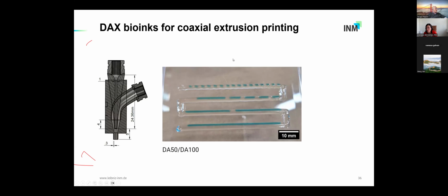So we use coaxial extrusion printing to produce these fibers. Here you have an example of the simpler one. We have a core shell, a coaxial extrusion nozzle. We have a core shell structure where the bits inside, you see that we have also segmented them. I'll come to that in a second. The part inside the core is containing the bacteria. Outside we have the biocontainment layer, and we are using two different types of pluronic mixtures. Same solid content, just by changing the ratio of acrylated and not acrylated ones, we can change the properties.